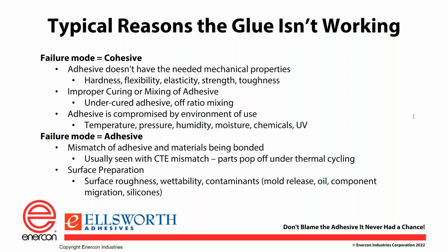For adhesive failure mode, where the adhesive just isn't sticking to your substrate, there may be a mismatch of the adhesive and the materials being bonded. So we see that with a coefficient of thermal expansion mismatch. What we typically see is that the parts are bonded and the assembly is thermally cycled. And during that thermal cycling, we'll actually see parts just spontaneously pop off of the assembly. That's due to as the assembly is heating and cooling, the different parts expand and contract at different rates, and that mismatch of CTE causes parts to just pop right off.